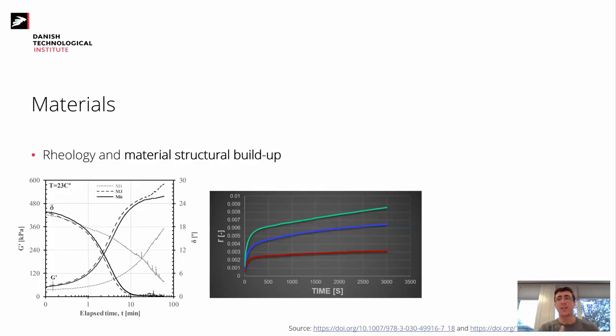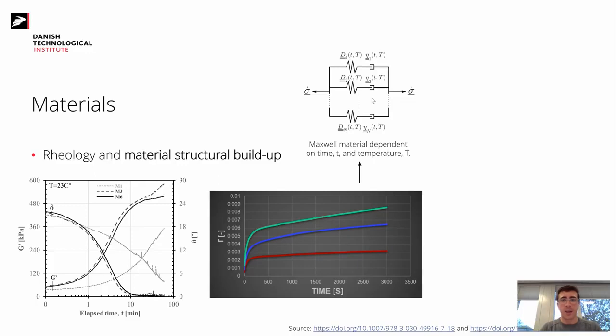I'm mapping the development of the storage modulus, in that sense the elastic response of the material to loads over time. And then in the black chart, I'm measuring the creep behavior. So when I sustain a load on a layer, how much is the deformation after the immediate load? So you have the compliance function, or how much the material creeps over time. And this allows us, again, to feed a different model. In this case, it's a Maxwell material, an elastic model with a creep response, which is dependent on both time and temperature. So the information from the chart on the left side gives me these components, and the information from the creep compliance will give me the deformation over time.